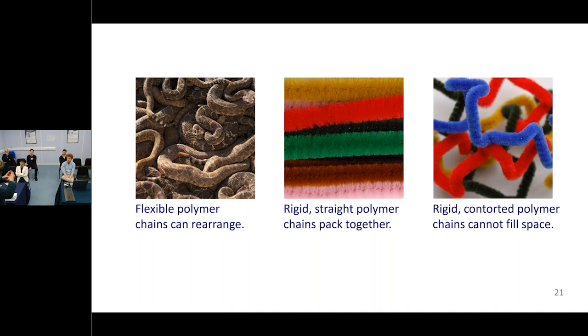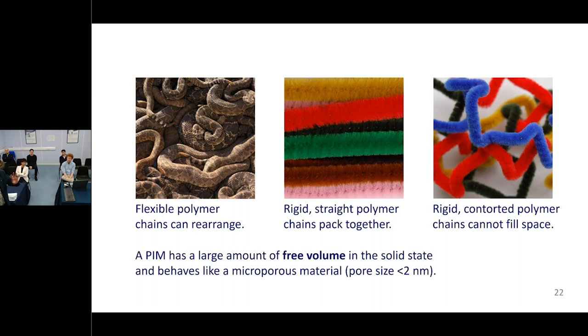And we do that usually by building structures which are a series of rings, like a tiny little molecular ladder. But we also make the chain twist and turn, so it looks like a wiggly polymer, even though it can't wiggle. And we do that by including what we call a site of contortion, something which puts a bend in the chain. In the typical example that I'll show you, it's a spirocenter. So the point about this sort of structure is that we now have a polymer which can't pack down very easily or effectively. It can't crystallize.